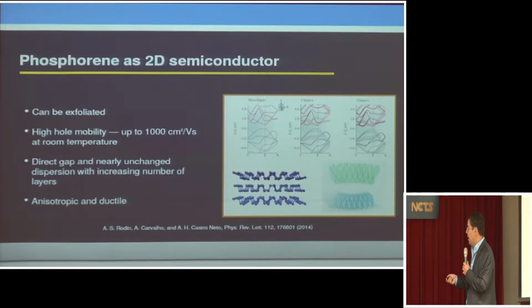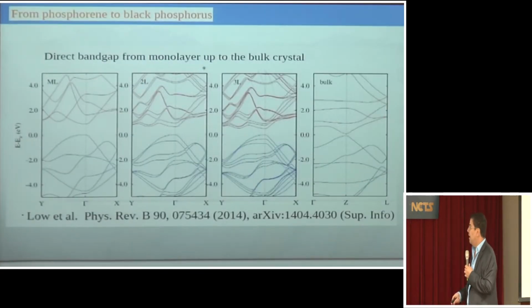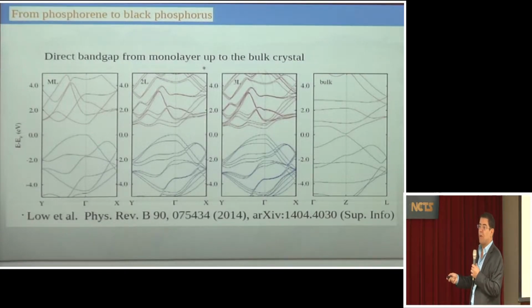All right? So, and you can fold, you can do all sorts of things. So, for instance, the gap is always at the center of the Brillouin zone, which is also very interesting for people doing optics, because you do direct transitions in the center of the Brillouin zone. And the gap changes with the number of layers, as I said before. Of course, life is not perfect. So here, but before talking about that, this is bulk. So the gap's around a fraction of a volt, and it goes to a volt when you go to the monolayer form, as I was telling you before.